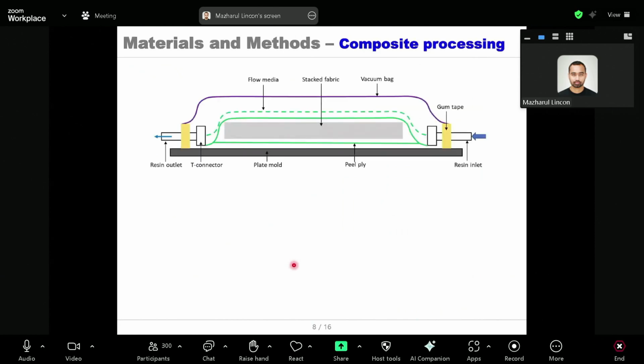Now, the composite specimen making procedure. A vacuum assisted resin transfer molding process is used to prepare the composite specimen. The flow diagram is shown here: this black part is just the Teflon board, and this gray part is the composite ply stack. The composite ply is covered with peel ply, flow media, and the vacuum bag, and the overall system is sealed with gum tape. From this inlet, resin passes through the composite specimen, and the excessive resin goes out through the outlet.